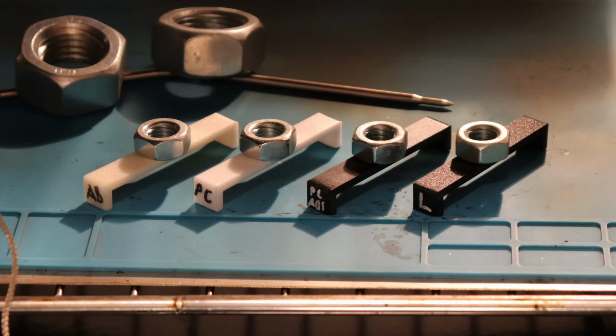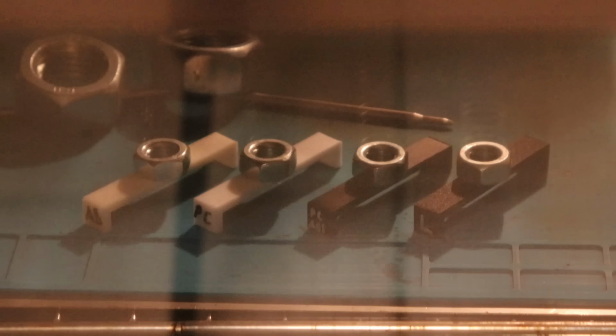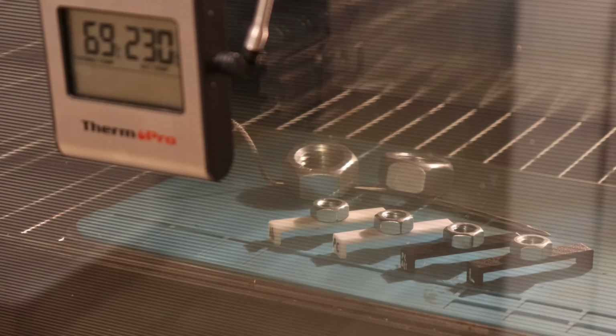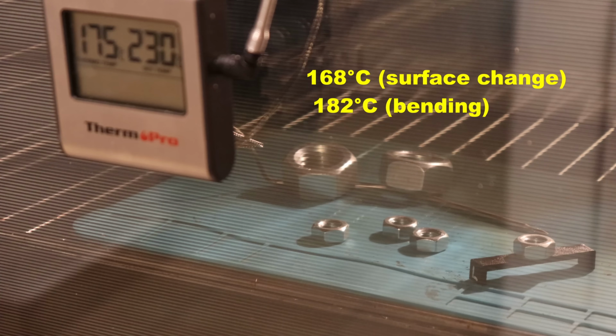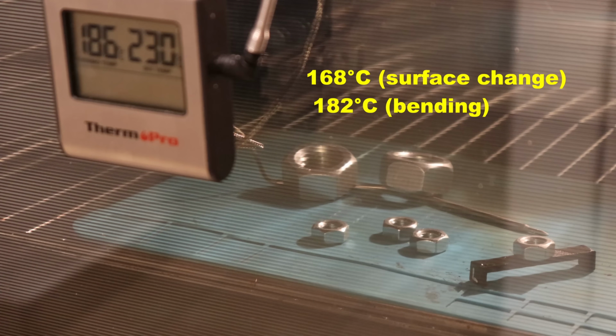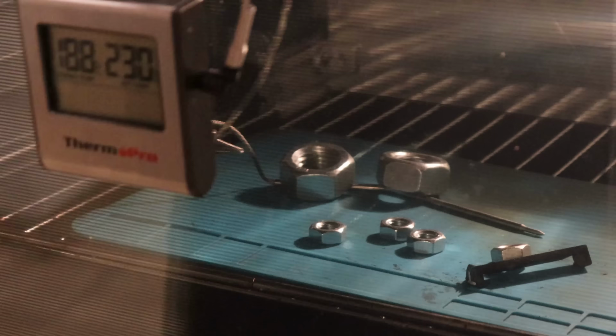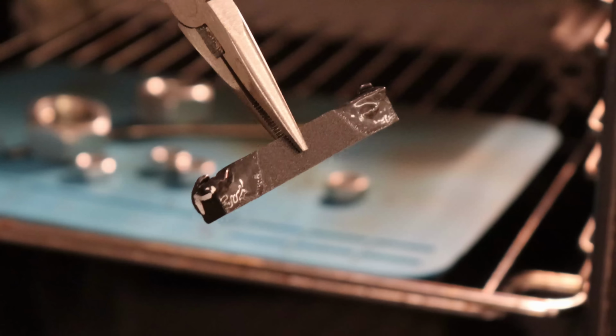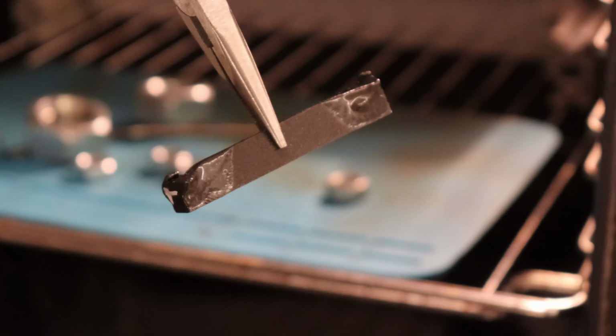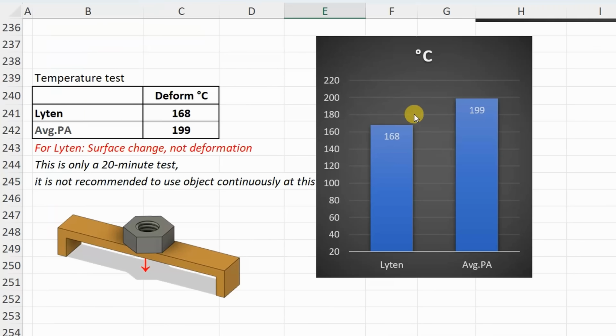Temperature test in the oven, and the one on the right side is this Lyten from this video. And I have several tests in progress, and the first 3 I had to take out earlier. And first surface change I noticed at 168 degrees Celsius, and only later it started with the bending. In summary table I will include the temperature of the surface change. For the Lyten, this is recorded number of the surface change. In theory, the annealing helps with the temperature resistance of the nylon. I'm not sure if that's the case with the surface change too.